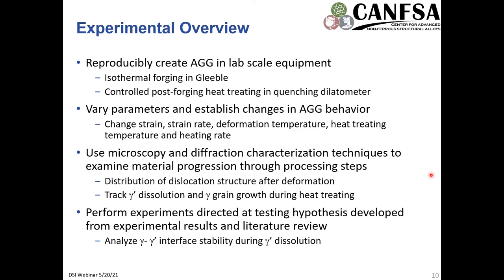And one of the really interesting and useful techniques was a technique in electron backscatter to look at the distribution of dislocation structure after deformation, and I'll go into a little bit more detail about that. We were also trying to track the gamma prime dissolution and gamma grain growth during heat treatment, so we tried to have some interesting experiments to do this. Utilizing these, we were able to iteratively develop hypotheses and test them about what is occurring. As we got further into the project, we really started looking at the gamma-gamma prime interface and the stability of that during the gamma prime dissolution.